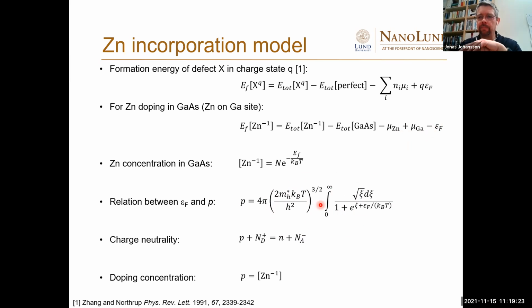But in our case, we have really hard doping. So we have a degenerate doping. So we have the Fermi level a little bit up in the band. So unfortunately, I need this full Fermi integral. Otherwise, it would be a big error introduced. Okay, we need an equation for charge neutrality. And since I don't add any donors, I put this to 0, and I also approximate this n to 0 here, the number of excess electrons. So I have only holes. So in that case, the doping concentration is given by the zinc concentration, which I calculate here using this relation self-consistently by plugging in this.